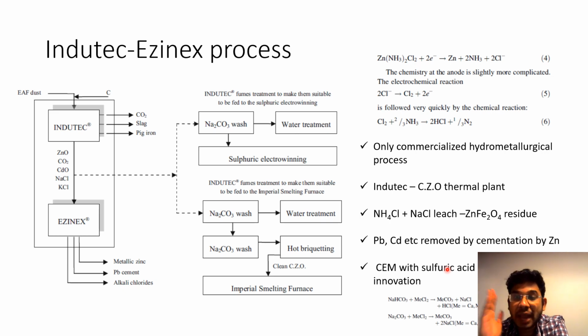You have a chamber in between in which you try to avoid the migration of the anions by just putting a selective membrane, and you fill up the other compartment with a non-chloride solution so that you just let the oxygen evolve. So you don't need to worry about chlorine evolution. That's one way they solved it.